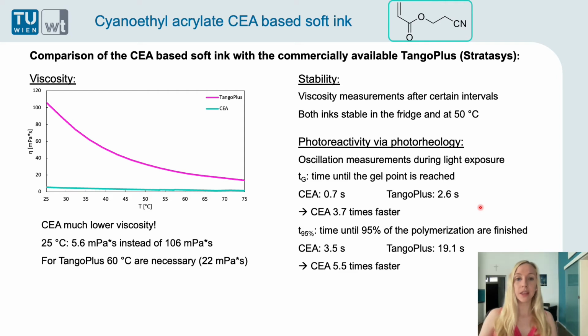And another important parameter is the time until 95% of the polymerization are finished, the T95%. And here the cyanoethyl acrylate needs only 3.5 seconds, while the Tango Plus needs 19.1 seconds. And this means in terms of T95%, the cyanoethyl acrylate is 5.5 times faster than the Tango Plus.